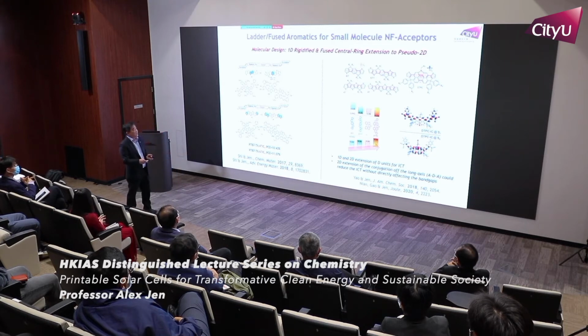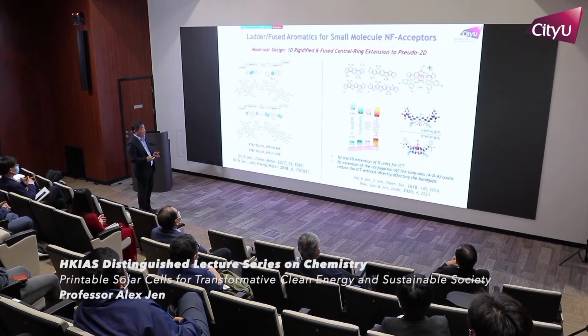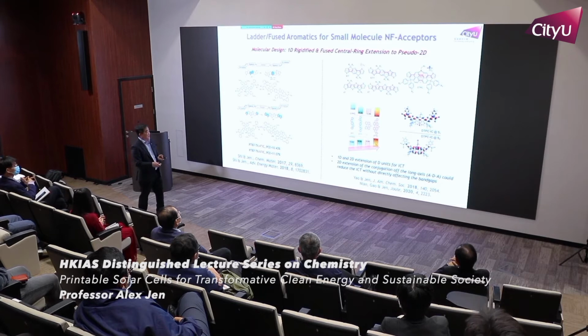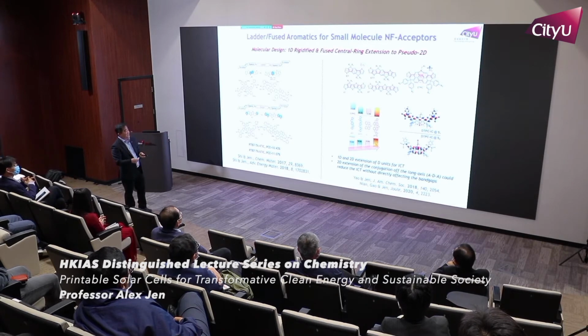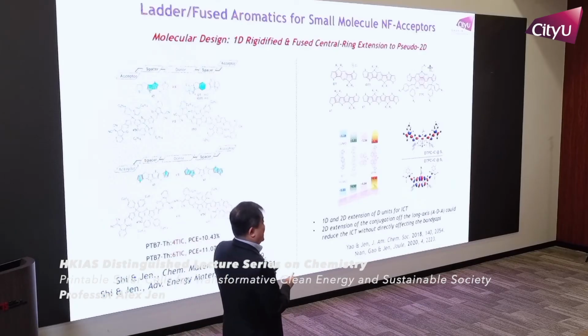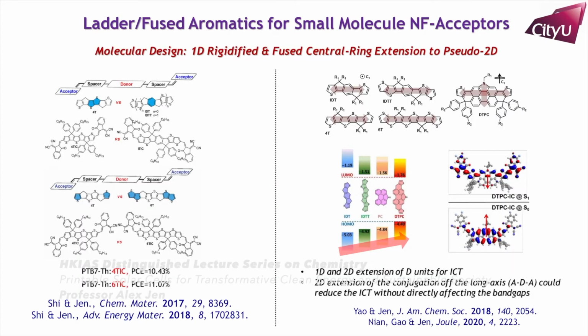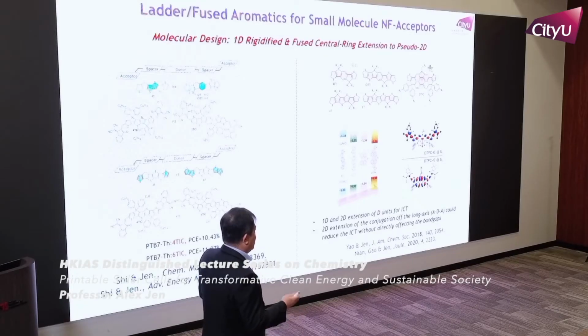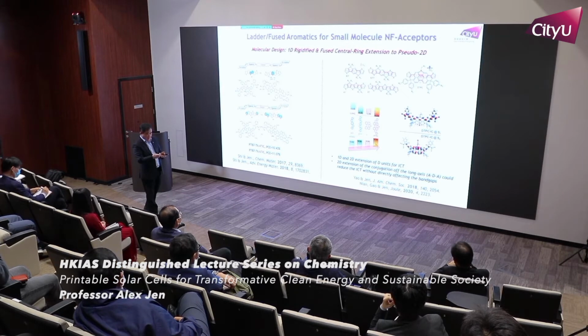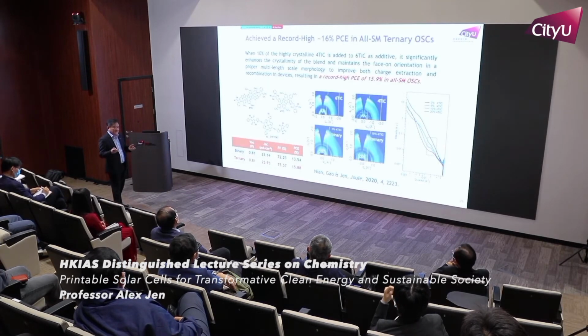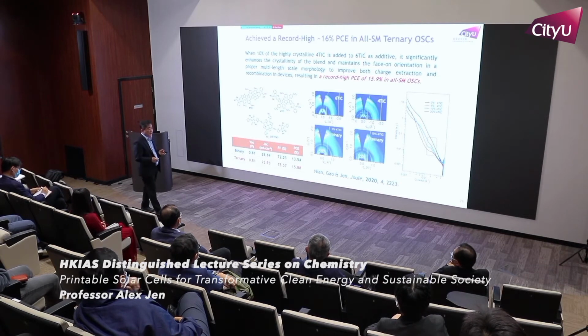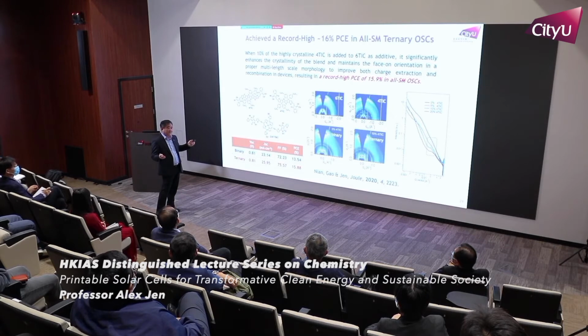So we took this into account. How do you develop a pseudo-2D type of molecular structure? In our JACS paper, we talk about not only having strong intramolecular charge transfer, but also, by utilizing a larger, more delocalizable conjugated backbone, you can have transient dipole moments, and then you can balance that transient dipole. As a result, later on I will have an example to show you, the so-called new development of non-fullerene acceptor called Y6 really gets a very high efficiency out of this.